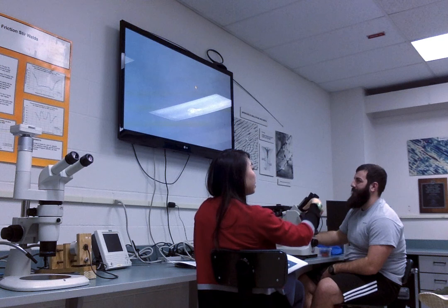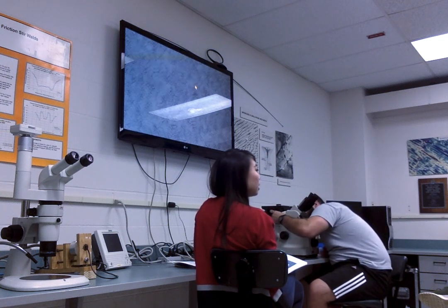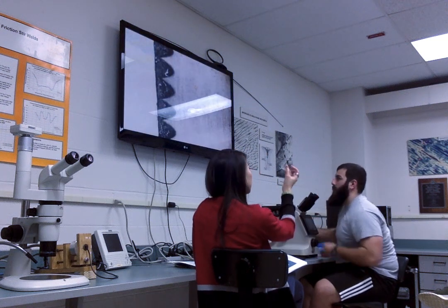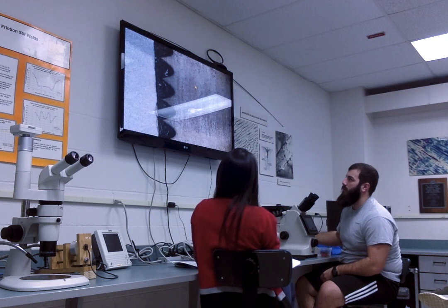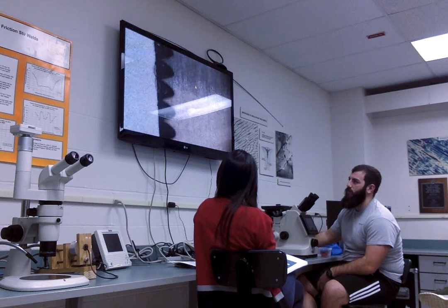And then you lay down a weld at the top of that threaded screw where it meets the weld. And what you do is you screw on a load that pulls down. It's a constant load on the weld, and if it cracks, this one obviously didn't crack. So this is where it got welded, this is like your screw, that's the heat affected zone up there, and this is where you attach it to pull your load.